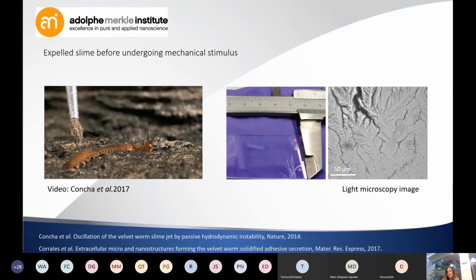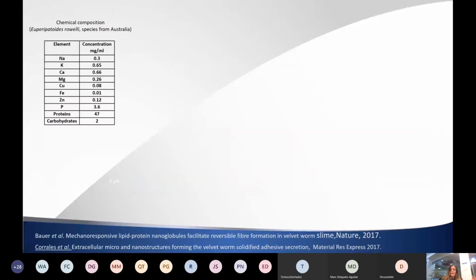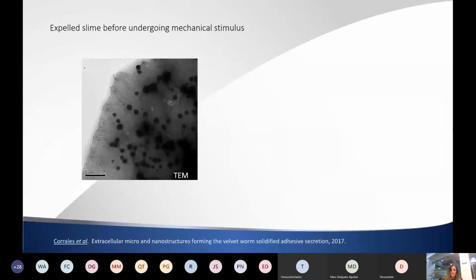So one of the first things we saw is that the material, when it's not mechanically stimulated, is white. So it means there is something changing the color, and after mechanical stimulation, it gets transparent. Under the normal microscope, the first thing we saw was that it has a lot of microparticles all spread all over the material. And we went further, I will explain this soon, and we could see that this material, without any staining, was full of these electron-dense micro and nanoparticles.